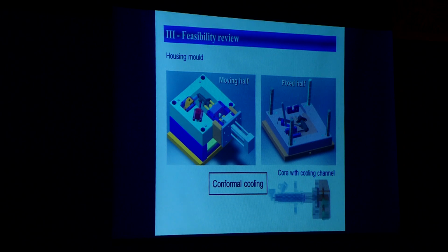The construction of the mold. Here we learned about the use of laser fusing, conformal cooling. The core had to be with very accurate temperature control. Otherwise, it was very difficult to achieve the surface finish. The surface finish is very critical for the plunger assembly movement. It had to have a surface roughness of about 0.2 Ra.